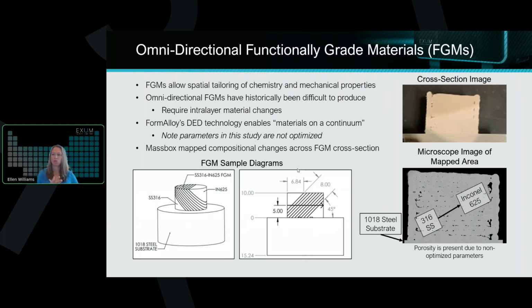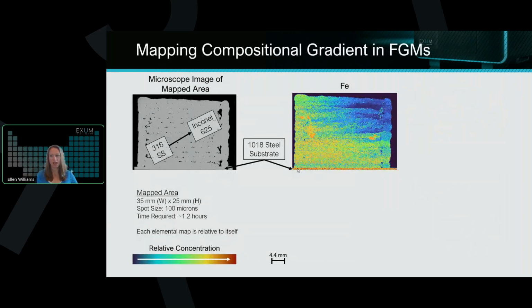And so what we did was an elemental map across this cross section in order to see those compositional changes. So you can see the microscope image there on the bottom right that we will then look at for the elemental changes across this area. So what you're seeing here is one of our elemental maps. In this case, we're looking at iron. For each elemental map, they'll be on their own relative scale, where the warmer colors, the reds, the oranges, are relatively high concentrations of a given element compared to the darker blues that are relatively low amounts of iron.